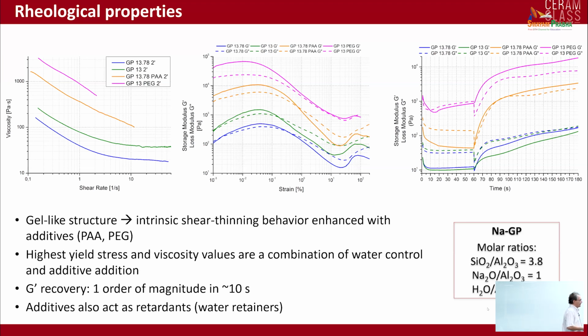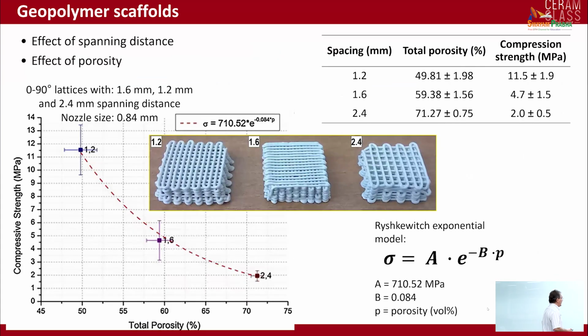So at the beginning, we modified the rheological behavior of geopolymer slurries using some additives such as polyacrylic acid and polyethylene glycol. And you can see that we were able to achieve better behavior, especially with PEG. And you can see the experiments for the recovery of the viscosity with time. The recovery is not yet ideal, but with these additives, it is improved. So, a 1 order of magnitude increase in G prime in about 10 seconds. So we worked a little bit for some time with this approach.